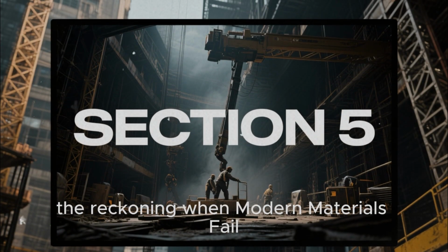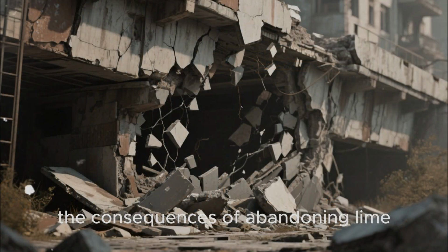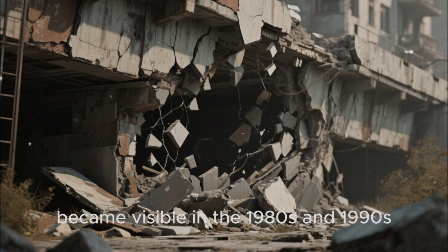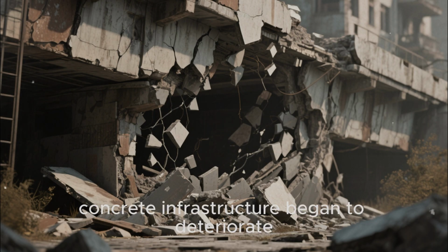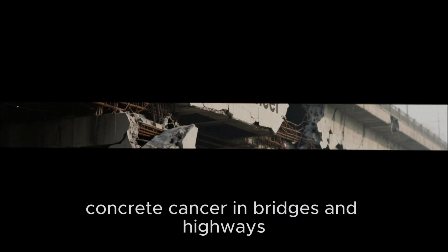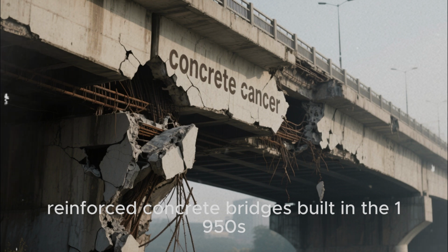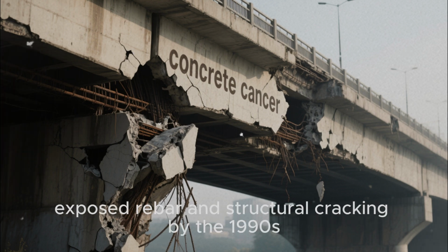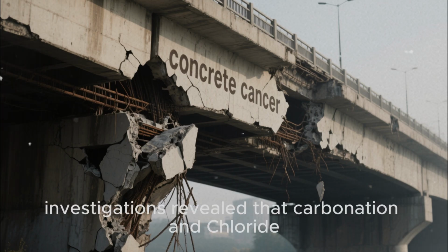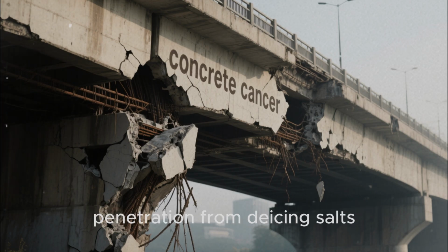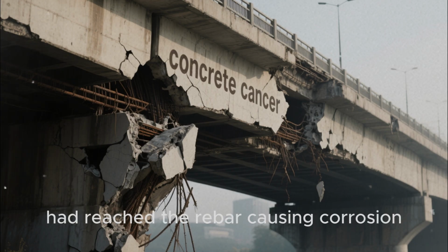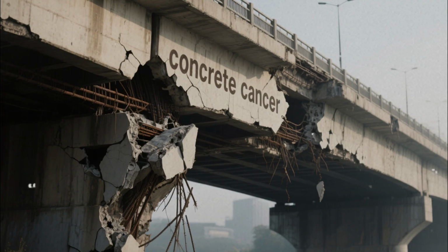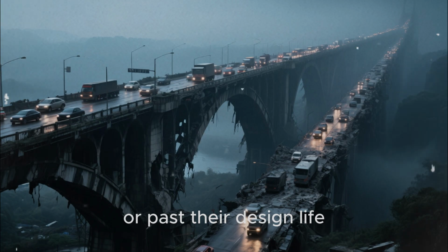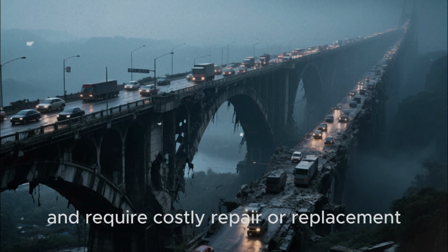Section 5. The Reckoning. When modern materials fail. The consequences of abandoning lime became visible in the 1980s and 1990s as the first generation of post-WWII concrete infrastructure began to deteriorate. Concrete cancer in bridges and highways. Reinforced concrete bridges built in the 1950s-70s started showing severe spalling, exposed rebar, and structural cracking by the 1990s. Investigations revealed that carbonation and chloride penetration from de-icing salts had reached the rebar, causing corrosion, expansion, and concrete failure. Many of these bridges are now at or past their design life and require costly repair or replacement.